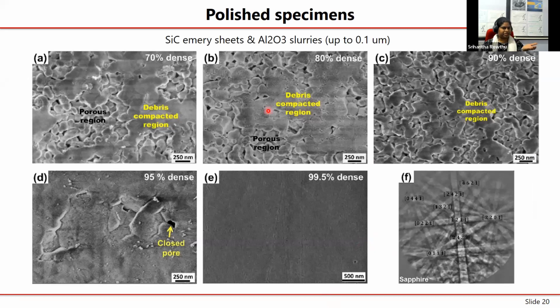These sintered samples, whatever we have got, we cannot directly use for our tribological testing, because the surfaces are going to have a lot of flatness issues. There will be a lot of waviness and also quite a lot of roughness, because your grains are not fully sintered. So it is definitely essential to polish the specimens. For that, silicon carbide emery sheets were used, followed by alumina slurries, almost up to 0.1 micron, or actually, it's wrong, let me correct it, it is 0.01 micron alumina particles in the slurries. I polished all the way from very coarse silicon carbide emery sheet using alumina slurries.